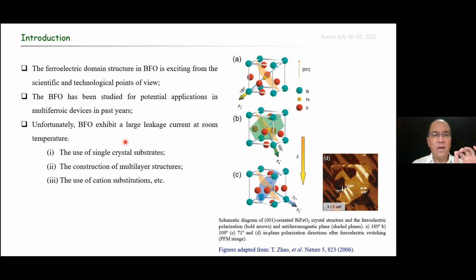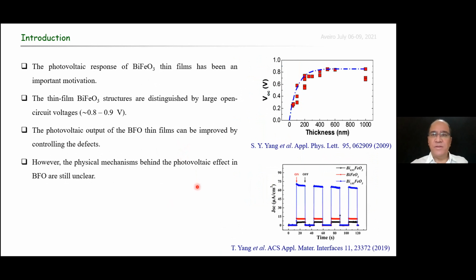However, unfortunately, a large leakage current is often observed in BFO thin films at room temperature. The use of single crystal substrates, the construction of multilayer structures, the use of cation substitutions, etc., have often been used as strategies to control the leakage current in BFO films. In addition to the large ferroelectric polarization, a large open circuit voltage and the photovoltaic response of BFO films have been an important motivation to study this system.